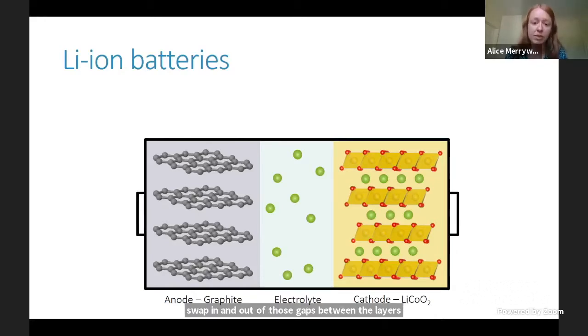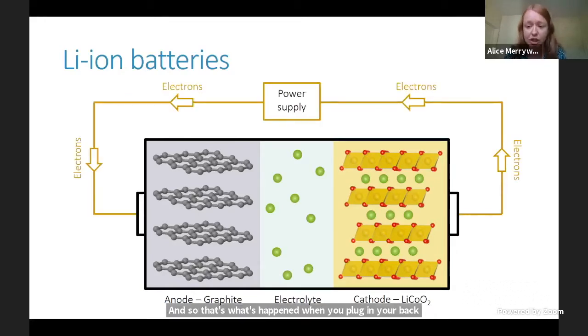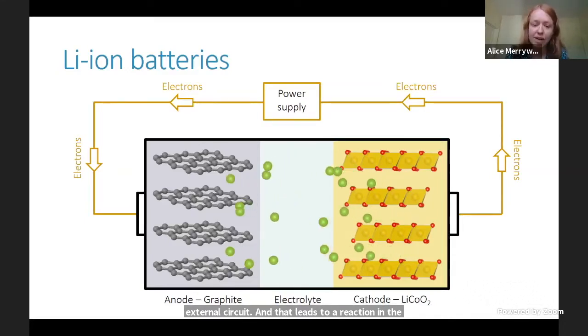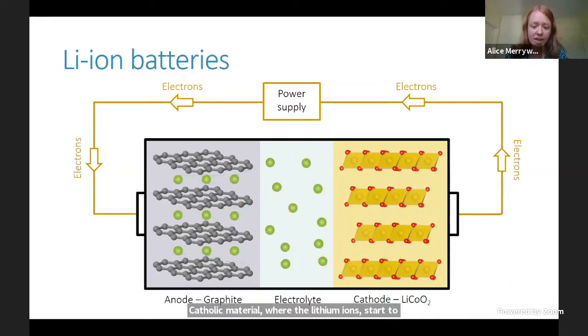And so that's what happens when you plug in your battery to start charging it. So when you're doing that, you connect up your battery to an external circuit and apply a current to the battery. And this means that electrons are flowing around that external circuit. And that leads to a reaction in the cathode material where the lithium ions start to come out of the layers in the lithium cobalt oxide, and they diffuse across the battery through this salt solution in the middle called an electrolyte. And at the same time, lithium ions are reacting with the anode and getting inserted into it.